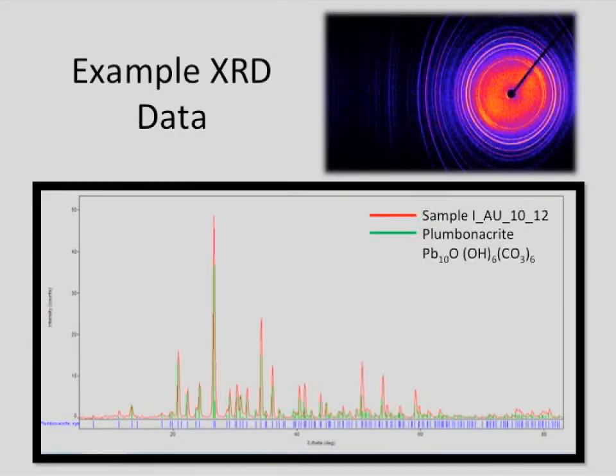With that kind of setup, we get data that looks something like this, where the amorphous ring we see is this bright area at the center near the beam. I've chosen an ideal image here for what data looks like, but that's easily subtractable out of the baseline, so we get a nice flat baseline after doing a background correction.